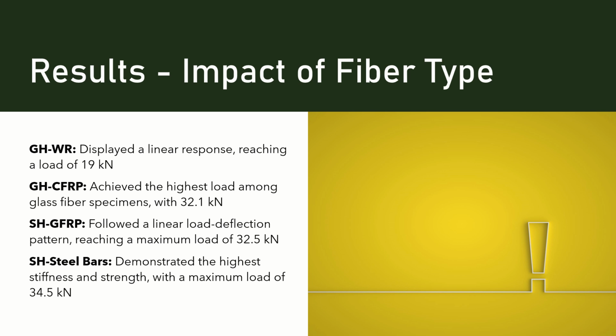When we examined the impact of different fiber types, we found that GHWR displayed a linear response with a maximum load of 19 kN. GHCFRP achieved the highest load among glass fiber specimens, reaching 32.1 kN. The SHGFRP specimens followed a linear load deflection pattern and reached 32.5 kN. The specimen reinforced with steel bars, SH steel, demonstrated the highest stiffness and strength with a maximum load of 34.5 kN.